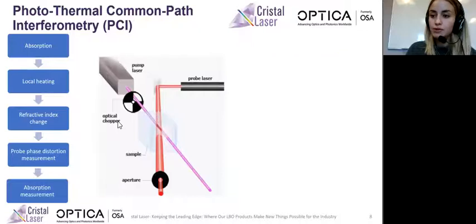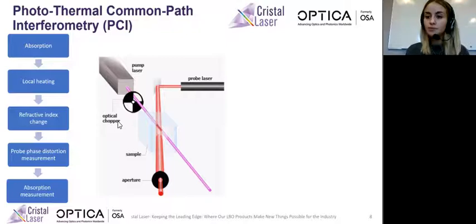The pump beam is going to be absorbed by the crystal, which will produce a local heating inside the crystal and cause a refractive index change, because the refractive index is temperature dependent. The probe laser then undergoes a phase distortion, which is measured, and the absorption of the optical material is derived from the recorded phase distortion. This technique is very useful because we can measure both the surface absorption of the coated crystal as well as the bulk absorption.